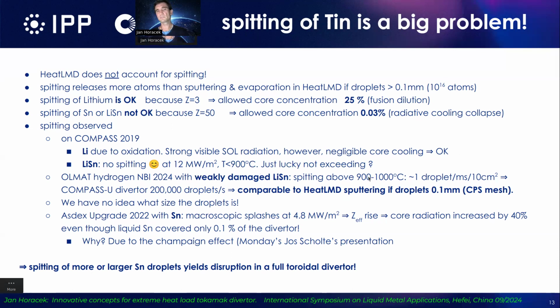And this limit we just saw in June this year in Madrid on the OLMAD experiment, that a weakly damaged lithium-tin target, exactly the same one, started to spit very strongly above 900 centigrades. And the amount of droplets is pretty high, 1 droplet per millisecond from the target, which if you extrapolate it to COMPASS, would mean nearly 200,000 droplets per second. And it would be comparable to sputtering and evaporation if the droplets are larger than 0.1 millimeter, which is quite the same size as the CPS mesh, so that's quite possible. We have no idea what the droplet size is, so this should be measured.